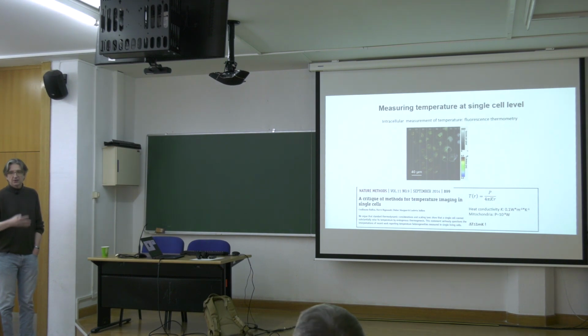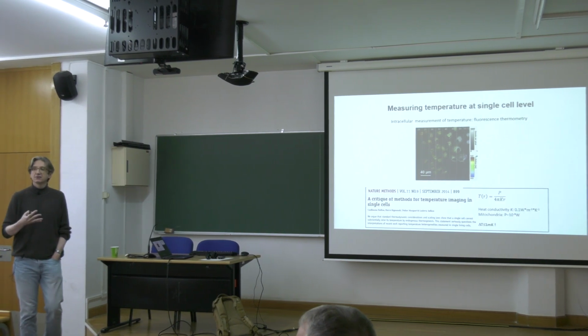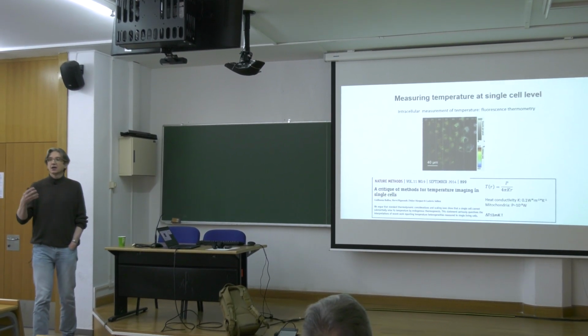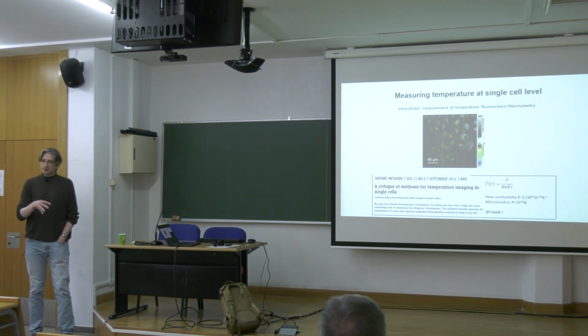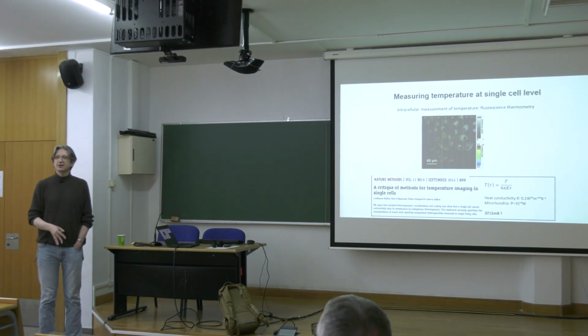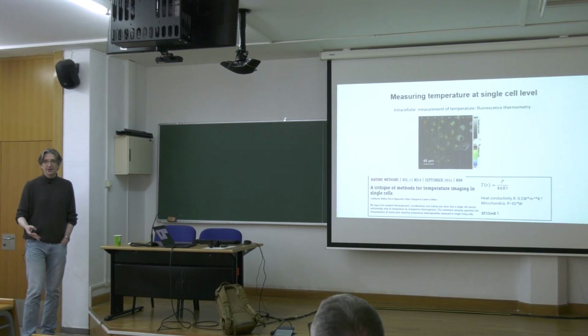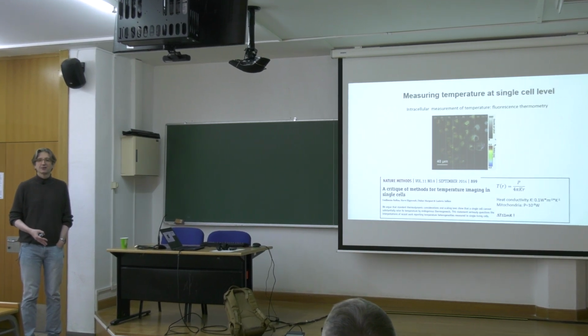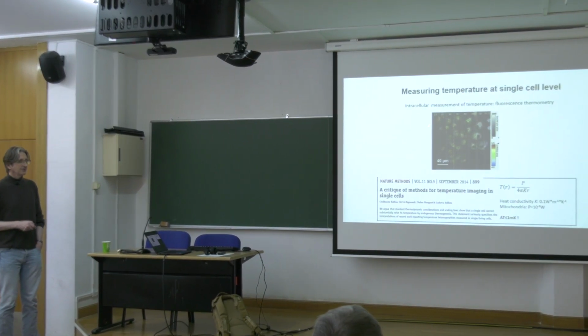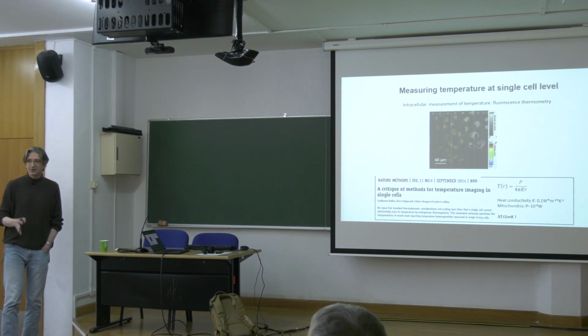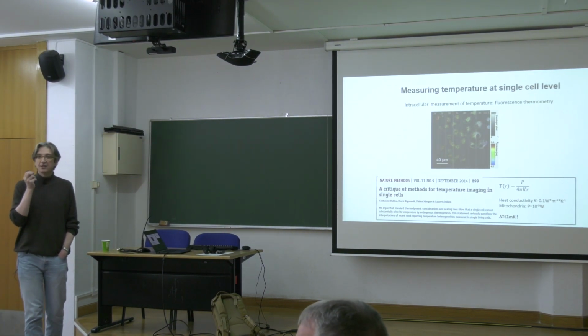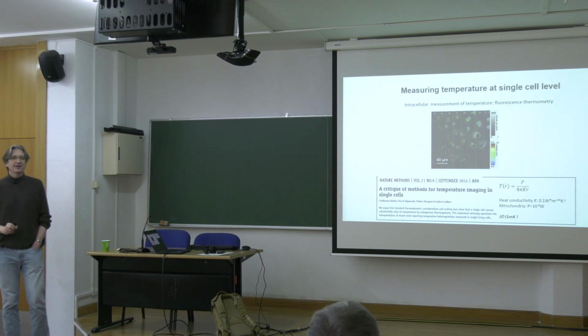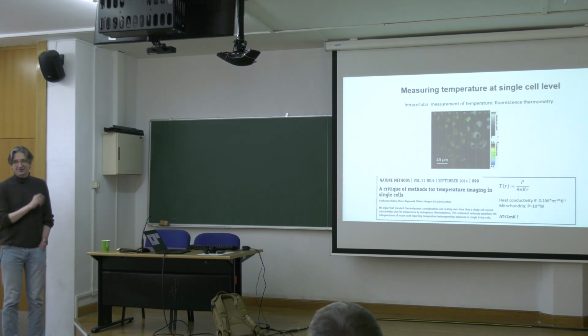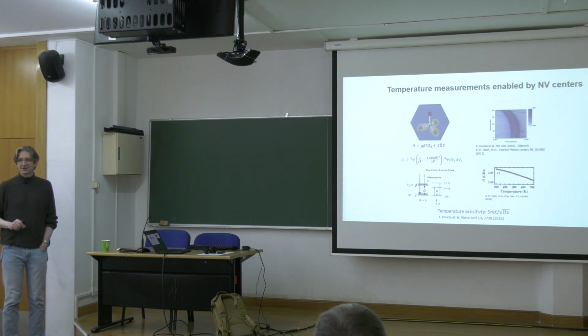And what was measured some time ago is that temperature gradients inside of cells, measured using this method, can be as large as a few degrees. So that created some discussion because that does not fit into the thermodynamic model of cells. If you take all the ATP that a cell produces or uses, you will not expect these gradients. You expect a gradient of a millikelvin. At the same time, the measurements show gradients of a kelvin. And this is still an open question in the community, so we don't understand very well thermodynamics on a single cellular level. So the thermometer is very much needed, and it's only one of the questions, but it's the most appealing question here.